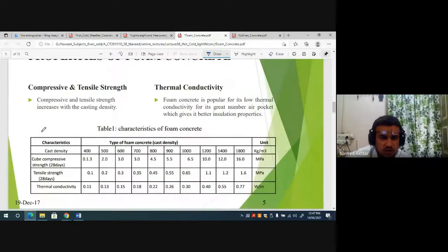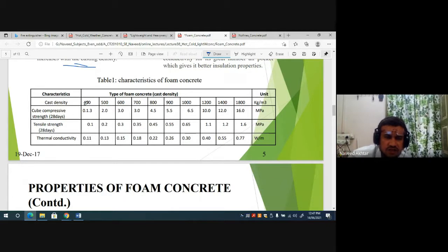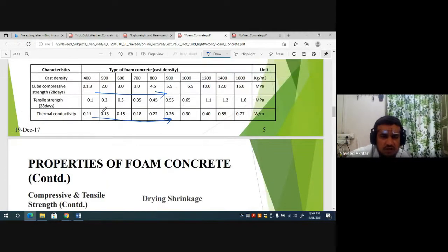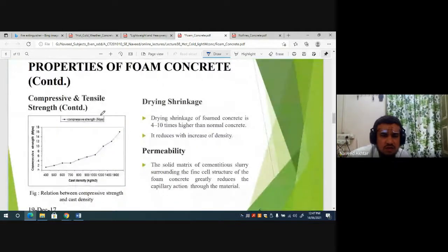What are the properties? The compressive and tensile strength increases with the casting density, and so does thermal conductivity. Foam concrete is popular for its low thermal conductivity. The heat transfer is low, so it may be used for insulation in hot weather conditions also. You can see the characteristic strength and density: as the density increases, the strength at 28 days also increases, and the thermal conductivity is also increasing. The drying shrinkage of foam concrete is 4 to 10 times higher than normal concrete. It reduces with the increase of density.